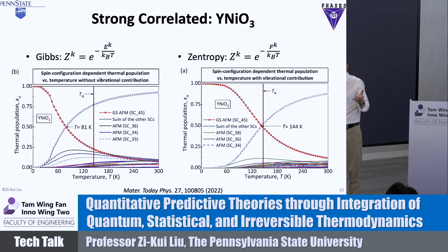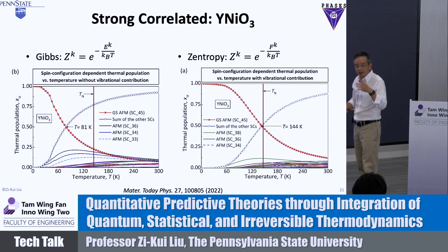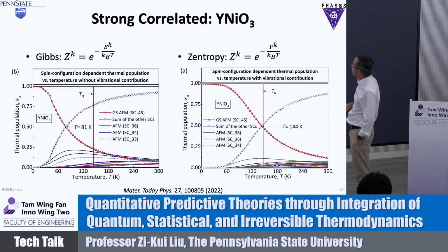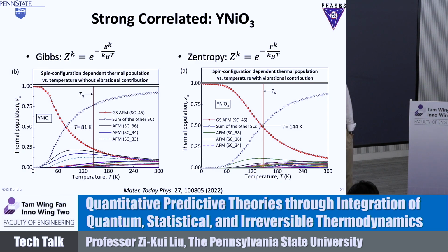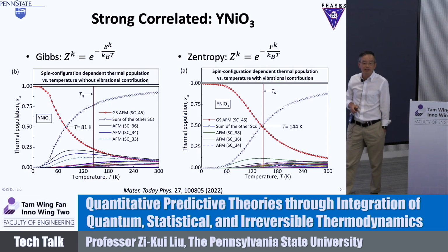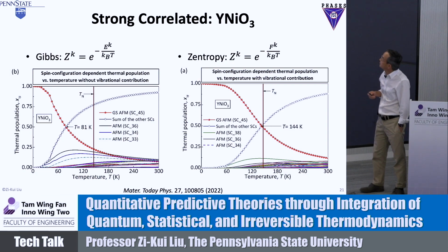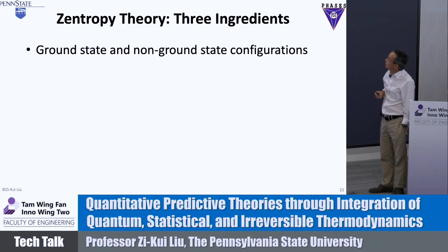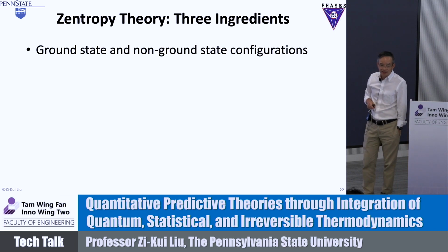That's actually what magnetic property measurement is about. Okay? Because you see the spin, the magnetization, which changes now from before. Magnetism goes to 0 because you don't have this well-defined magnetization anymore. Okay, so I hope I convinced the people that strongly correlated systems are strongly correlated because we don't understand them. It's not because it's strongly correlated, it's just because you have not sampled enough of the configurations to put them back together.